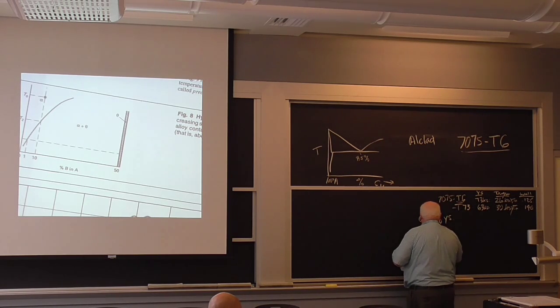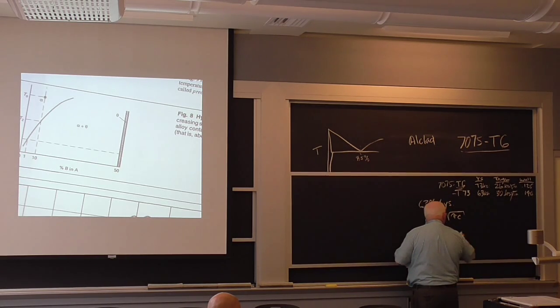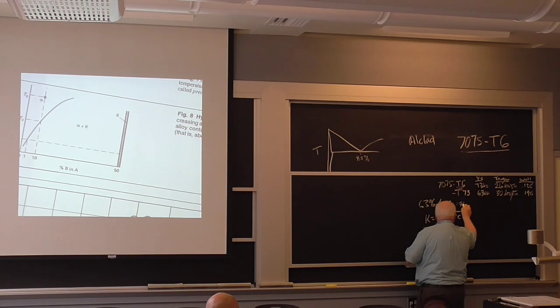And you have the fracture toughness is equal to sigma times the square root of pi c, where c is the crack length. And we want the crack length to be greater than the wall thickness, so it'll leak before it breaks. And so K is 26 for the T6. Sigma is, turns out, 46 KSI for the T6 condition, equals, turns out there's a 1.12 multiplier out here that I've told you guys about, times square root of pi c.